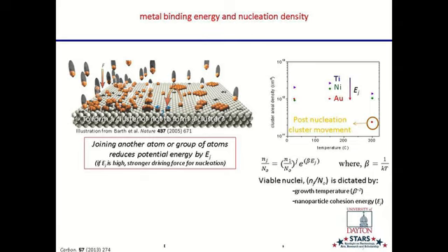For nickel, you can make them out. And for titanium, you really got to squint to be able to see. These are like the emperor's new nanoparticles, right? I can tell you that they're there, and maybe you'll believe me if you're really smart, but maybe you won't. Really, we need another tool besides an SEM to be able to see them because they're so small. But this is a nice figure, and it shows you that there are some physical limitations to this approach. We need the particles to be a certain size to get the kind of functionality that we want, but the size is limited by nature.